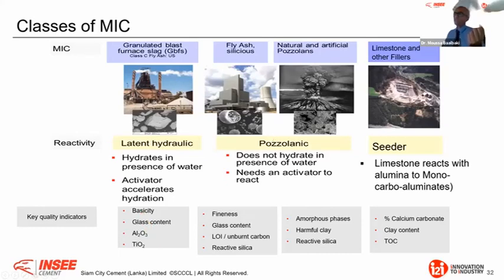After that, for the fly ash, for example, fineness, glass content, loss on ignition, unburnt carbon, reactive silica, also standards put limitations for the use of this fly ash. When it comes to natural pozzolan, the same: amorphous phases, harmful clay, because they are very heterogeneous, coming from a quarry, a natural deposit. Very often you have harmful materials, especially clay. So very often those materials have high water demand. And of course, the reactive silica to assure certain reactivity.